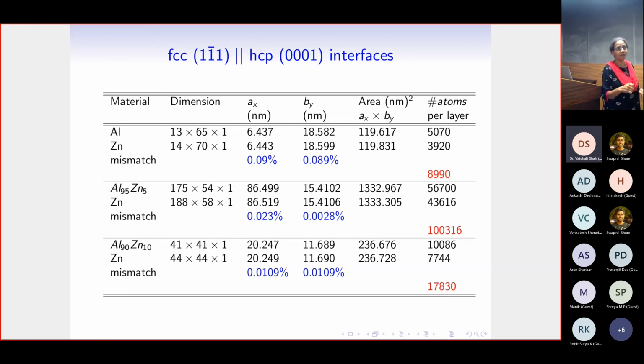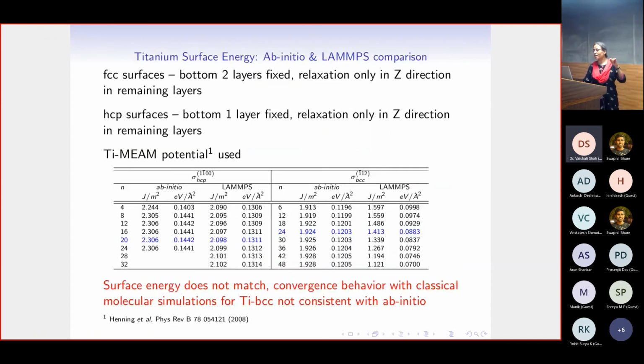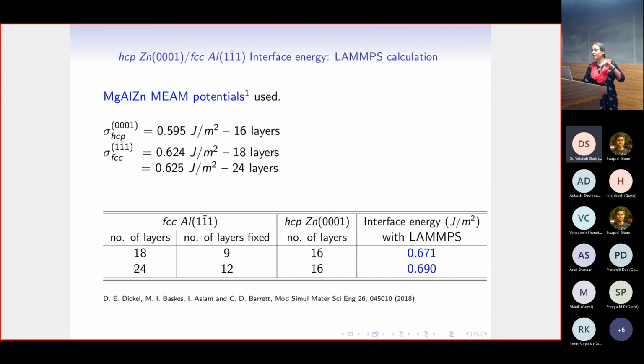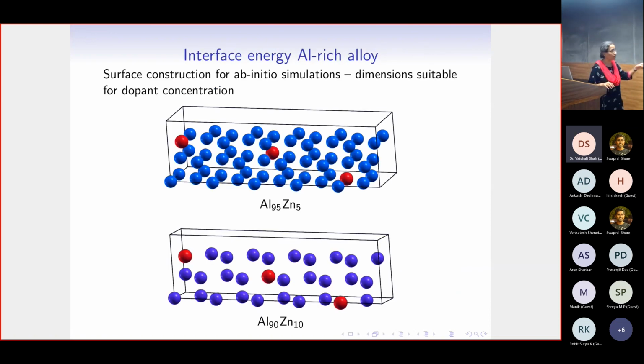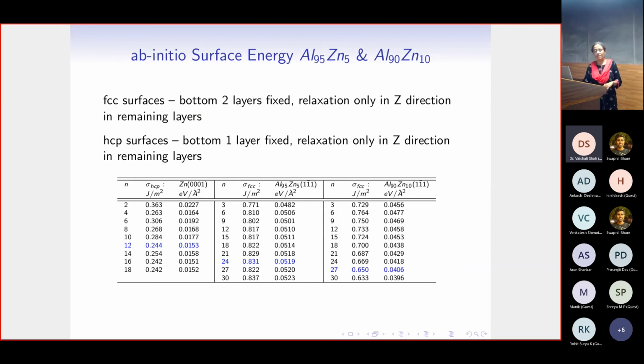Right. I understand. So when we did the surface energy convergence studies here, I didn't tell this, but for this case, for 95/5, we went to 30 layers. So 30 layers means already I have a 600 atom calculation there. And when I go to 90/10, because as I increase the dopant concentration, I require smaller cells actually, it came down to 300 atoms.